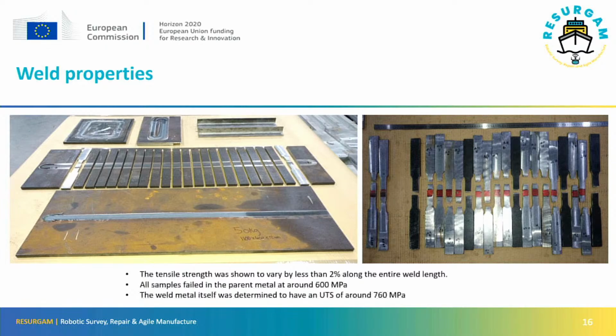So what we did then, and where these black samples are, every fifth sample, we cut a very sharp edge notch into the weld, 2 millimeters deep, in a 12 millimeter plate, so that we were forcing the failure to take place in the weld metal. And when we tested those, we were finding that the weld metal was showing us a strength of 760 megapascals. So the weld was 25% stronger than the parent material we started with.